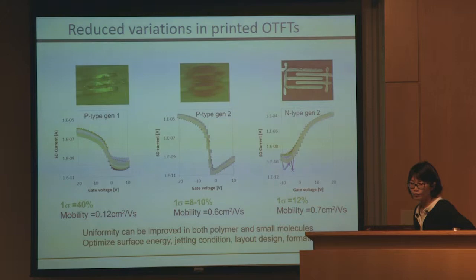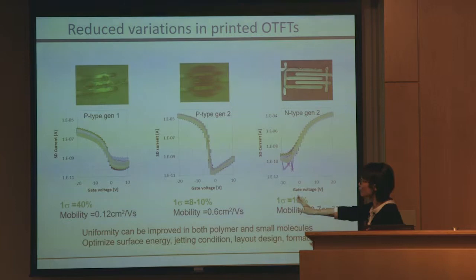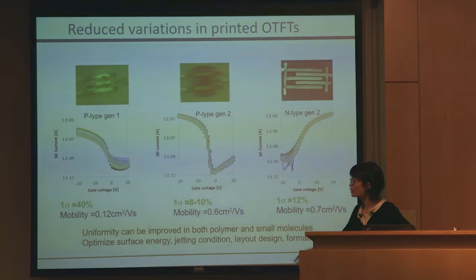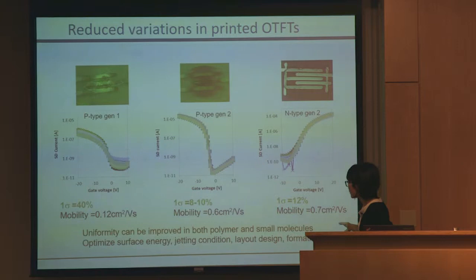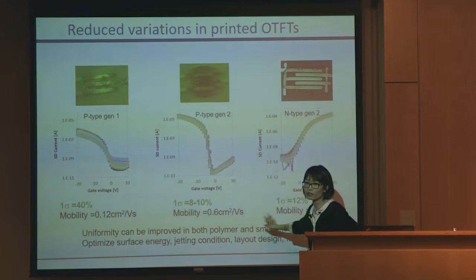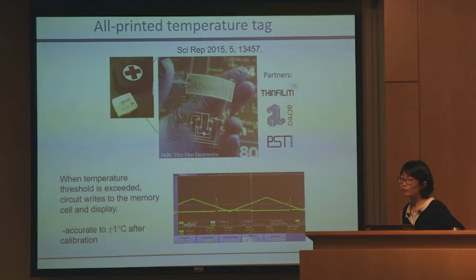And so, yeah, different generations of the transistors are shown here. The first generation, they work, but then there's too much variation, up to 40%. And then as time goes on, we control the printing parameter much better. We control jetting condition, layout designs, etc. And we were able to reach the target of 10%, which give us 85% yield. And so that's how we were able to build more complex system out of this.